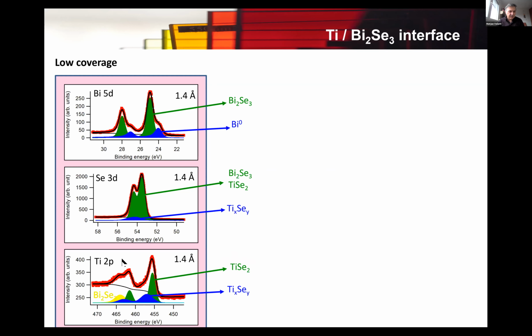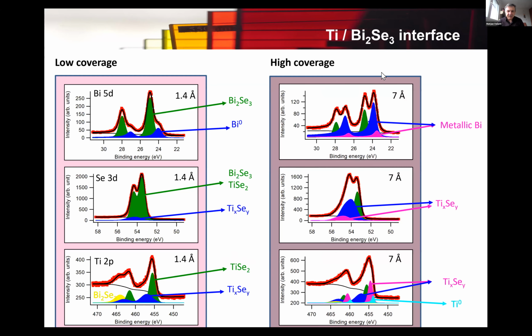And that was done for low coverage, and a high coverage, high titanium coverage just confirmed all these processes. More metallic bismuth, more titanium selenide in both cases. Here we also see some metallic titanium which has not yet interacted with the surface. So we are very close to writing down the chemical reaction that is happening at room temperature.